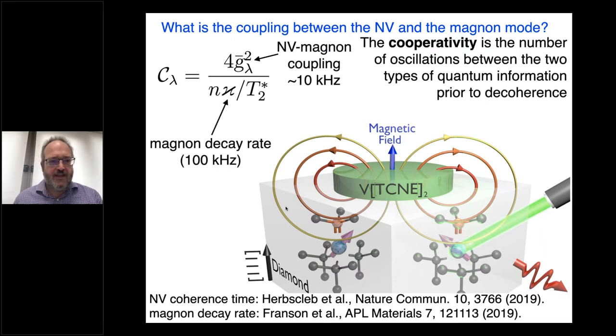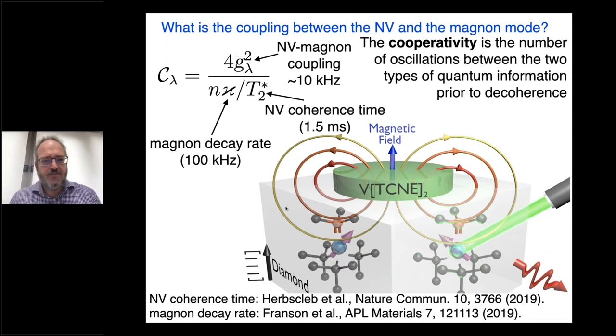So the pieces that go into this are an NV magnon coupling, which we calculate for this geometry, for reasonable parameters, to be about 10 kilohertz. You also need a magnon decay rate. Here's where the low loss is essential. For this material, it's about 100 kilohertz. And then you need an NV coherence time, which in some of the best material is in excess of a millisecond.